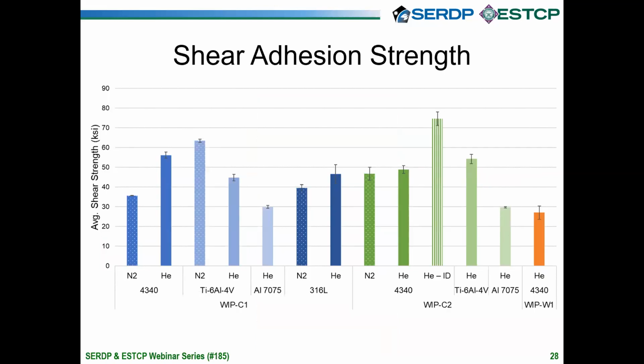The next thing that we evaluated is shear adhesion strength, and we evaluated this using lug shear testing. We also evaluated our coatings on a number of different substrate combinations. What we found across the board is that all of our coatings and substrate combinations had at least 20 KSI shear strength. Now, there isn't really a comparison for chrome plating because with chrome plating, you can't do lug shear testing because that testing requires you to build up enough thickness of material that you can machine a lug, and you can't do that with chrome plating.